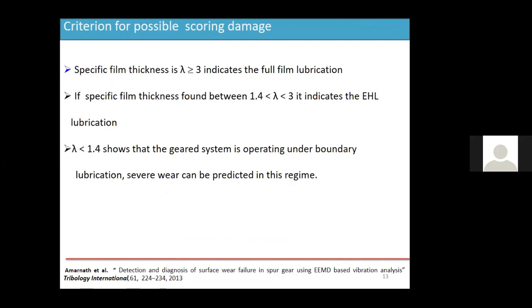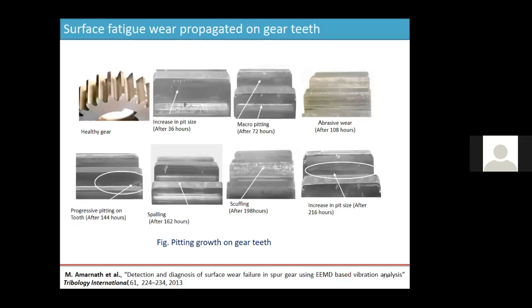If it is between 1.4 and 3, then it is the EHL, elasto-hydrodynamic lubrication regime. If it is less than 1.4, then the gear system is operating under the boundary lubrication regime. Then maintenance action is supposed to be taken during the boundary lubrication regime. So this is the criteria for possible scoring damage. Because of the change in transition of lubrication regime from hydrodynamic to elasto-hydrodynamic and then boundary lubrication regime, there will be a propagation of wear on gear tooth contact surfaces in this fashion. You can see increase in pit size, scuffing, spalling, progressive pitting, etc.